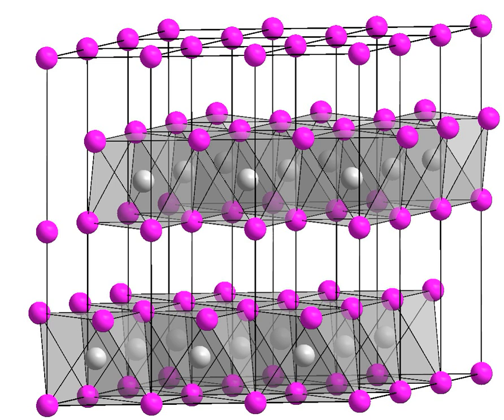The compression behavior of titanium disulfide is anisotropic. The axis perpendicular to the Ti-S layers, the c-axis, is more compressible than the axis parallel to the Ti-S layers, the a-axis, because of weak van der Waals forces keeping S and Ti atoms together. At 17.8 GPa, the c-axis is compressed by 9.5% and the a-axis is compressed by 4%. The longitudinal sound velocity is 5,284 meters per second in the plane parallel to the Ti-S layers. The longitudinal sound velocity perpendicular to the layers is 4,383 meters per second.